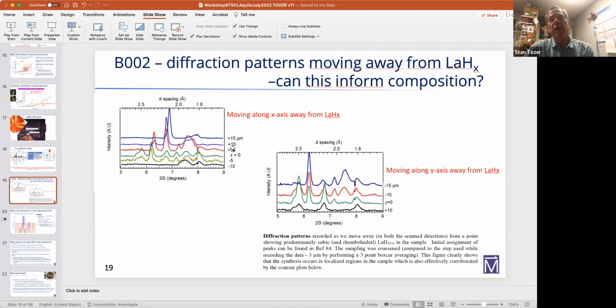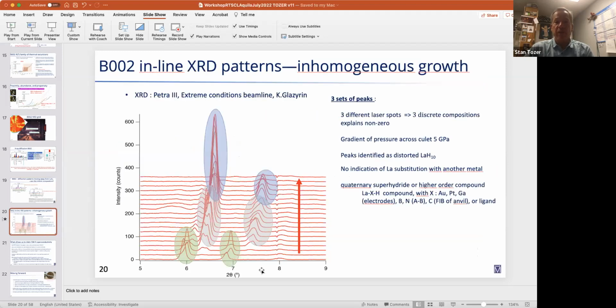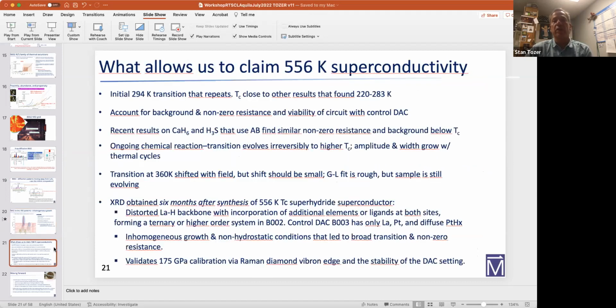If from the star we move out away from that star, we find that the composition changes dramatically, both in x and also in y. So this is going to lead to that very broad transition that we see, and also the non-zero behavior. And then the arrow that I showed was horizontal, but now we're looking across here in this waterfall. These are three discrete synthesis or laser spots, and you can see that the synthesis was discrete and very different in these three spots. Again, that would cause issues with non-zero resistance and the broad background below Tc.